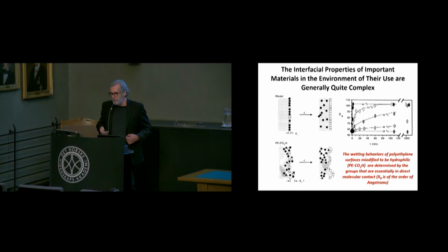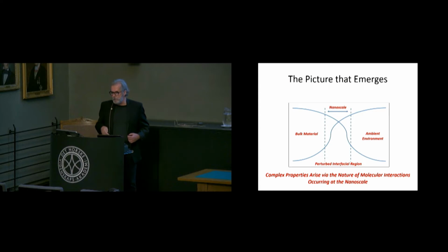And the really interesting part is if you look at the chemical composition of this as determined by a surface-sensitive spectroscopy, the composition hasn't changed at all, at least not detectably by those kinds of techniques such as X-ray photoelectron spectroscopy. And the picture that emerges from data like that is that at the nanoscale, there's a structural characteristic that leads to the wetting behaviors that you see.